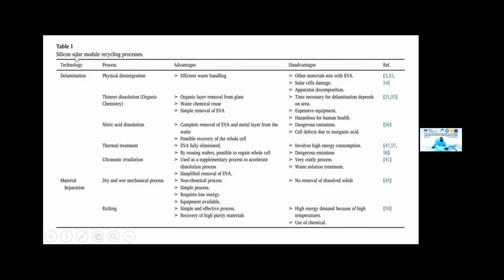So this is the silicon solar cell module. This is the physical separation. This is the advantage and disadvantage. There are many processes for thermal treatment. We can see the EVA layer: with nitric acid dissolution, it completely removes the EVA metal layer from the wafer, but is dangerous for emission. And if we follow the thermal treatment, EVA is fully eliminated. This is the advantage, and the disadvantage involves high energy consumption.